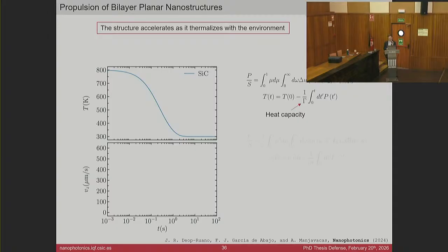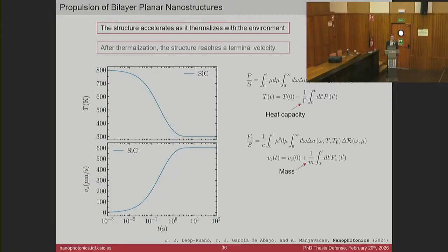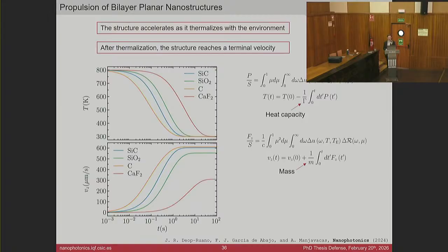In the case of the velocity, we have to integrate the force acting on the nanostructure. And we can see that, as we suspected, the nanostructure accelerates as it thermalizes. But once thermalization is completed, it reaches a terminal velocity. And of course, this terminal velocity is going to depend a lot on the properties of the nanostructure, both the optical properties and the inertial quantities, the heat capacity and the mass. It also depends on the initial conditions.